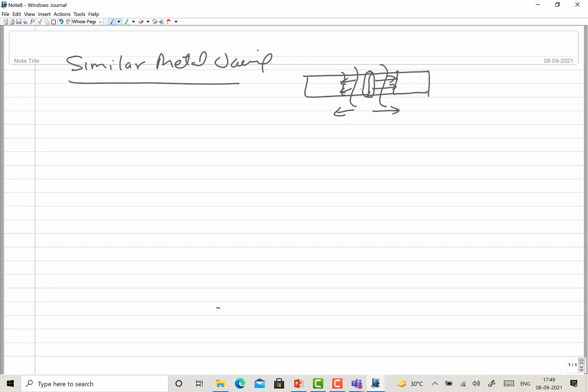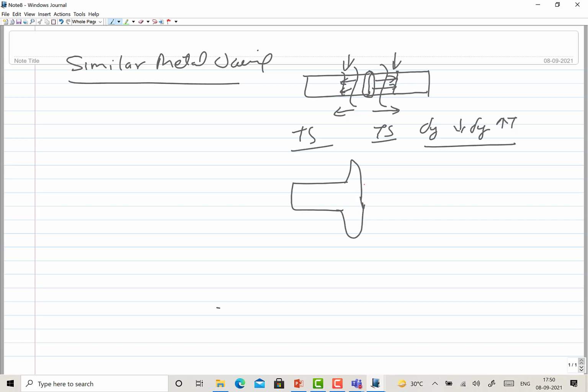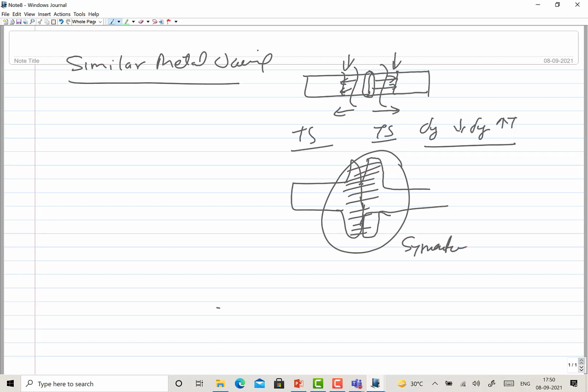And another important thing: since both metals are the same, their yield strength, or the drop in yield strength due to the rise in temperature, is the same on both sides. So if the thermal softening is equal on both sides, you can expect that upsetting will also be the same on both sides. You see, both sides will be getting upset by the same magnitude, right? Like this. So if the upsetting is equal on both sides, there is at least a symmetry in development of the weld.